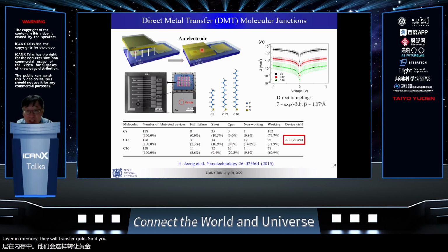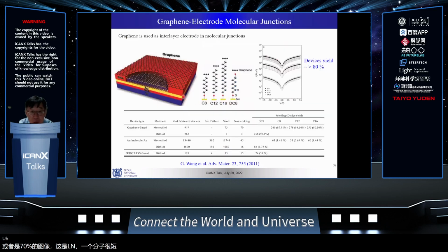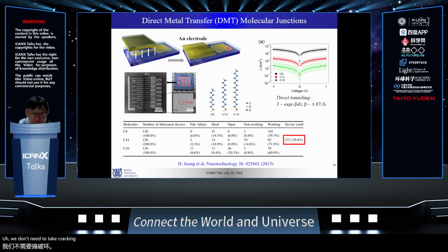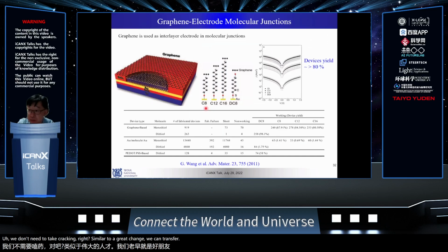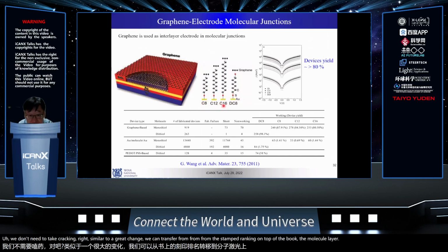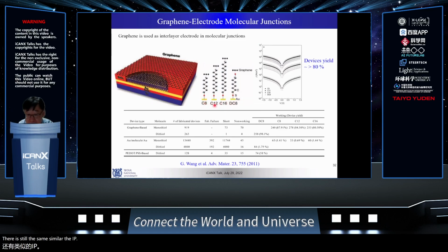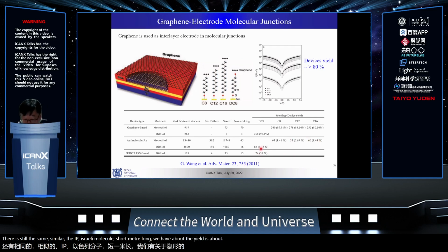So this can be a conventional gold molecule, gold junction, but the transfer yield is about 60% to 80%. Okay, or average about 70%. So this is an insulating molecule, short, middle, long. You can see this. We do that with graphene, right? Similar to graphene, transferred from the stamp to graphene on top of the molecule layer. So it's still the same, similar. The insulating molecule, short, middle, long. The yield is about 60 to 70%.